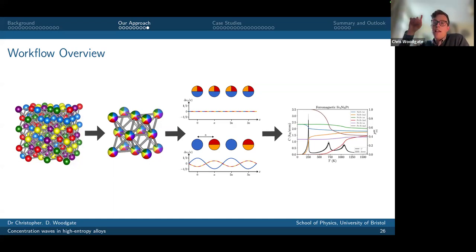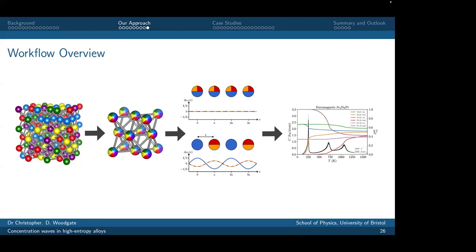So at high temperature, there's an L1-2 ordering with platinum moving to the corners of the FCC lattice, and then there's another ordering where, because there's a low enough concentration of platinum, there's an additional ordering on that sublattice, and then finally there's an emergent ordering between the iron and nickel atoms at a lower temperature.